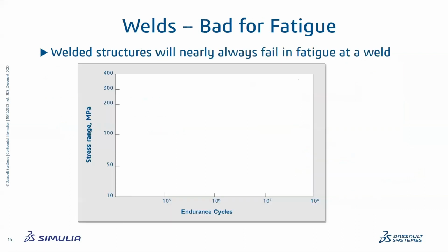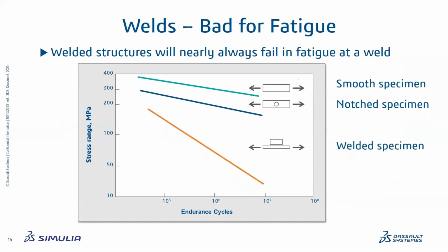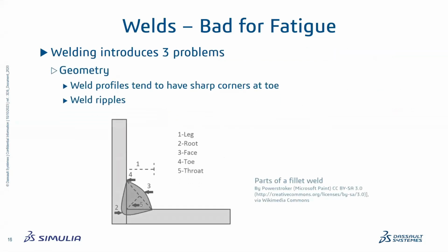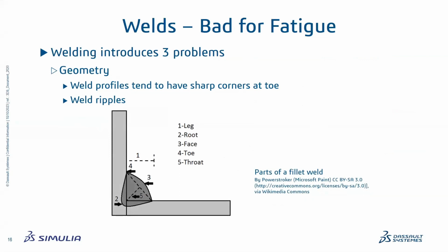So why was that? Well, it's basically for three reasons. This is just a chart showing the poor life of welds versus even notched specimens of parent plate. But why do welds have such bad fatigue life? There are basically three problems, at least the way I'd like to break it down. The first is geometry. Whenever you put a weld in, you will automatically have a sharp corner. Typically, if this wasn't welded together, there would be a fillet in here to smooth that out. But with a weld, you just get a sharp re-entrant corner.